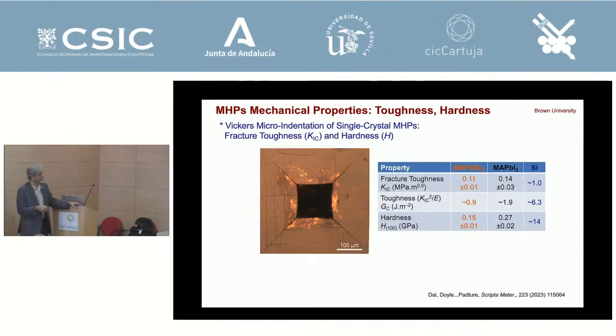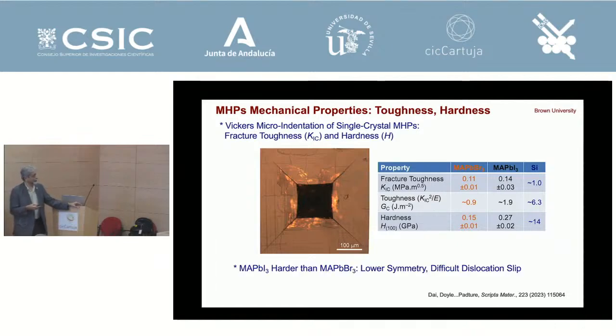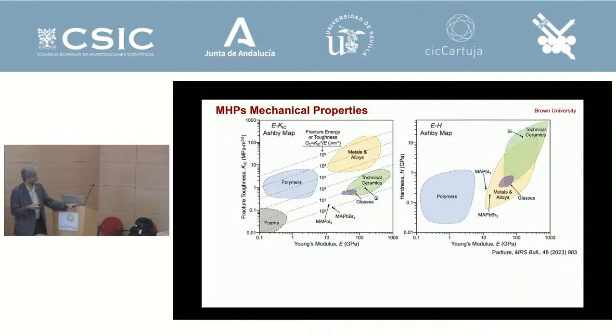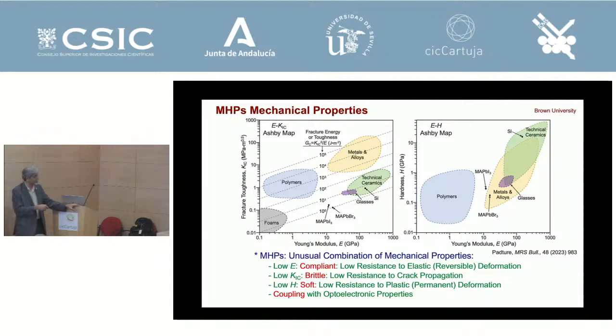And so this is 0.15, 0.3, this is silicon is about 14, alumina is about 19, diamond is 40, right? Anyway, so that's the story there. And so if you look at this and put these on these Ashby maps, you will see that they're sort of in the white space. So they don't fall in any particular category. They are a very unusual combination of properties.